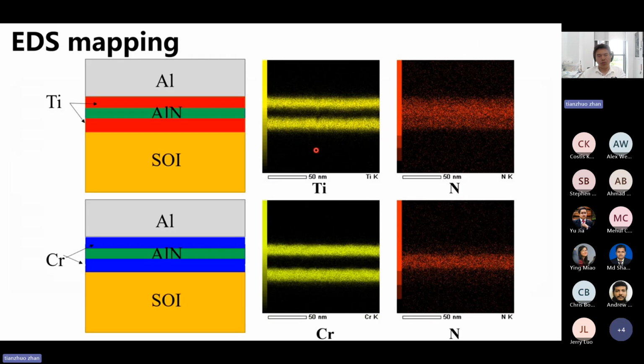And also we have observed the EDS mapping of different samples. We found that the nitrogen diffuses easily into the titanium layer, but with a little difficulty into the chromium layer. And this is also a possible reason for enhancing the heat transport between different layers, resulting in a lower thermal boundary resistance, and then a higher thermoelectric power generation.